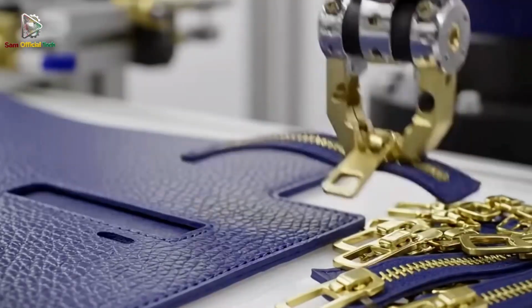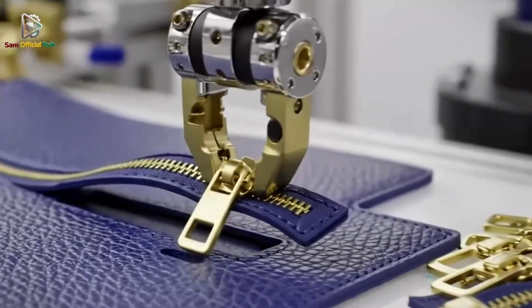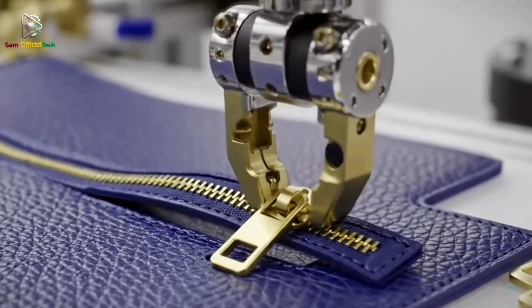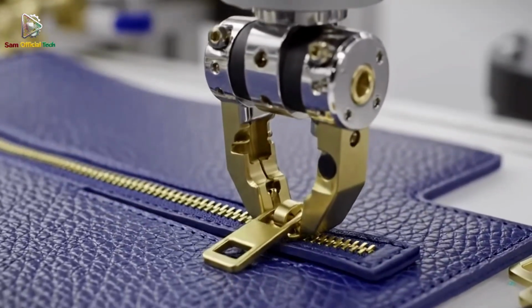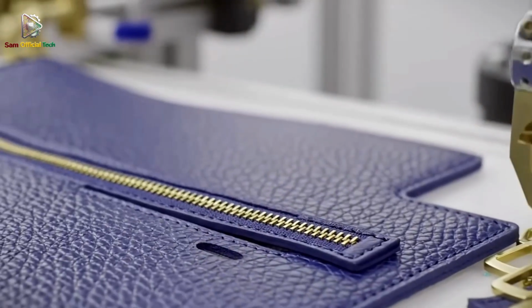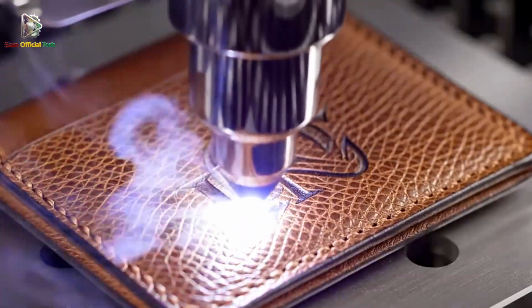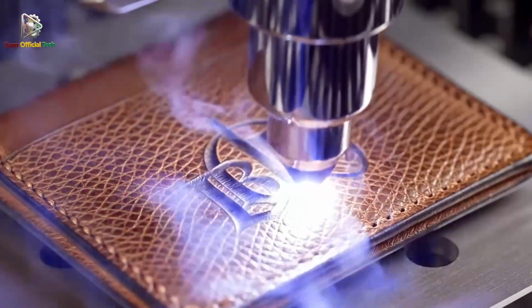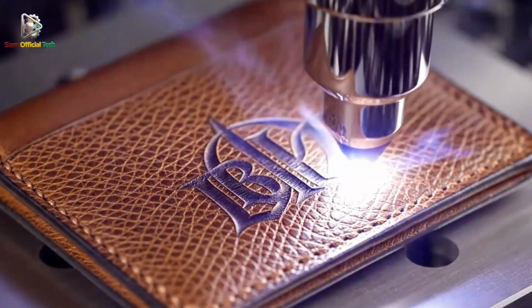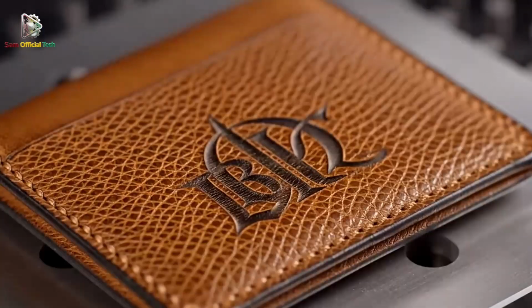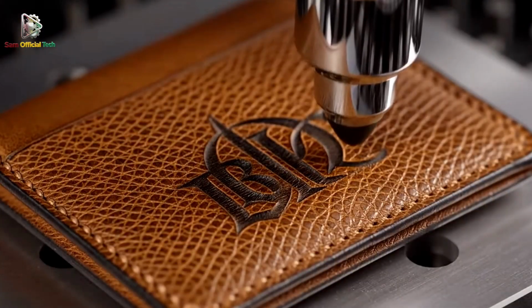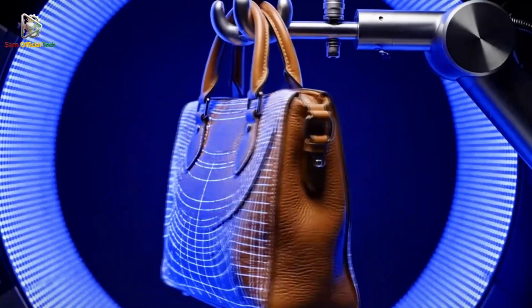What makes this process high-tech is that it turns an agricultural residue with massive natural variability into a repeatable, luxury-grade material by controlling structure at every scale. Fiber length and cleanliness are controlled in extraction and washing. Strength is built in non-woven formation. Flexibility and durability are tuned through impregnation and coating chemistry. And the final aesthetic is manufactured through embossing and multi-layer finishing.